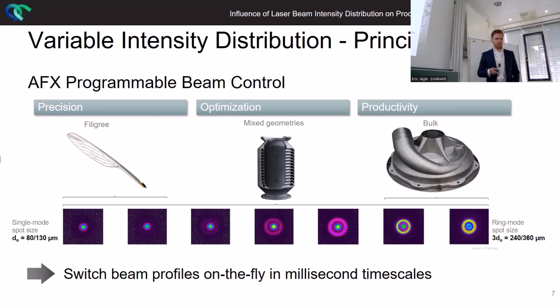One way to influence this process is through different laser beam sources, and for that, nLIGHT developed the AFX 1.2 kilowatt laser with 7 different intensity distributions. This is the standard Gaussian one on the left side, up to the ring beam on the right side, and 5 more different intensity distributions in between, differing in the power ratio of center and ring, so that it's possible to print filigree parts, mixed geometries, as well as bulk parts for productivity reasons, for example. One important thing is that you do not need any additional setup to shape your beam, but you can switch the beam profiles within a millisecond timescale on the fly within the process.